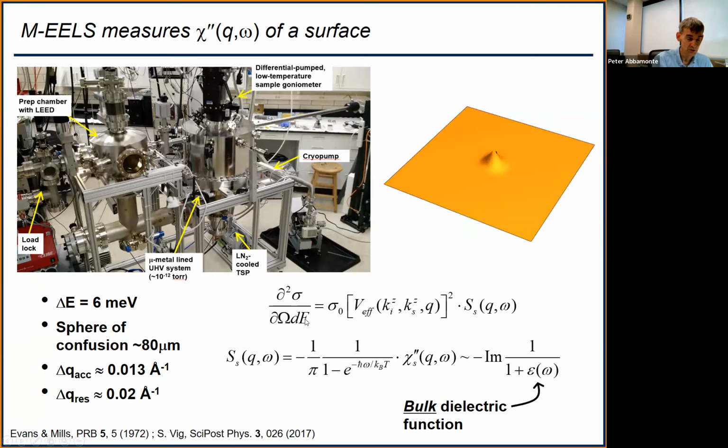I'm really doing scattering not with plane waves, but with this combined incident and reflected wave. So if you look in the sigma naught, the reflectivity of the surface is in there. That all goes into the derivation of the cross section. That's why this is a surface response and not just the bulk 3D chi that you compute with RPA. It's also the reason why we had to examine a different sum rule. So what can I say? It's a pretty validated method. It's been around for half a century, a lot of measurements. It seems to work pretty well describing the data.